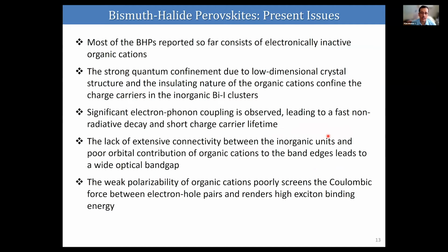But the present issues of bismuth halide materials are summarized here. So far, most of the reported bismuth halide perovskites consist of electronically inactive organic cations, like methyl ammonium or formamidinium. They are electronically inactive and cannot contribute to the overall electronic properties of the materials. In addition, these form low-dimensional crystal structures, and because of the low-dimensional nature, there is a strong quantum confinement effect in these materials. Since they use insulating organic cations, the charge carriers are confined at the inorganic bismuth iodide clusters. They cannot move to the electrodes, so these are not really suitable for photovoltaic applications.